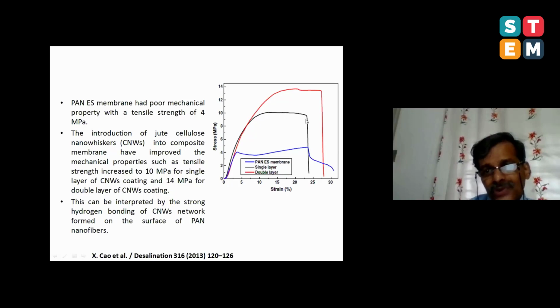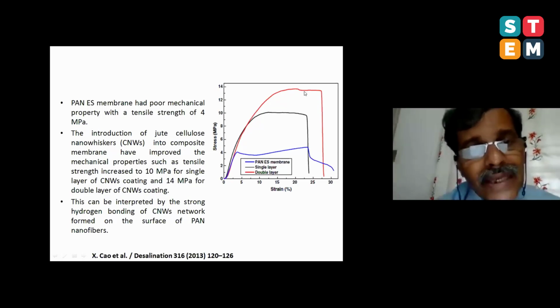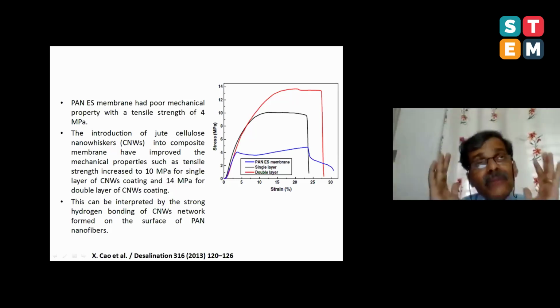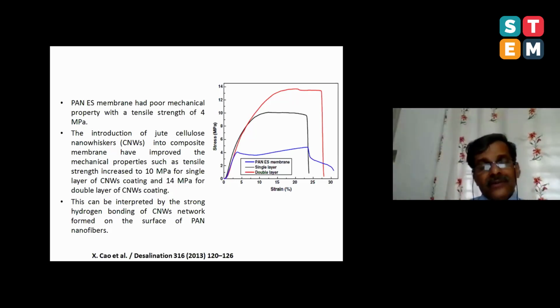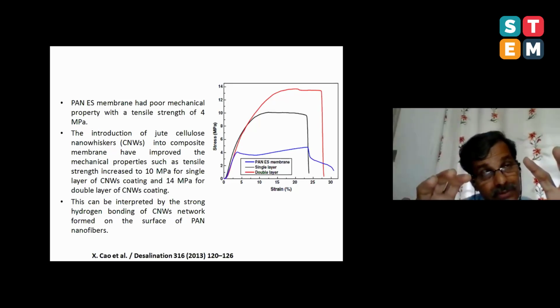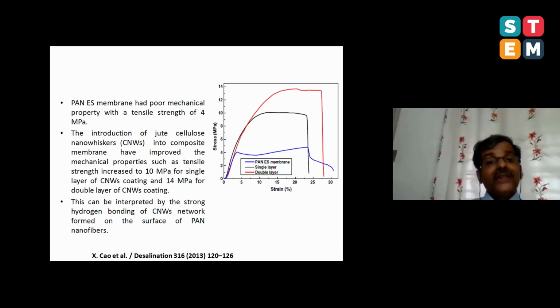But if you coat one side of this PAN membrane with nanocellulose, look at the stress strain behavior. If you coat both sides of this membrane with nanocellulose, look at the stress strain behavior. So what I want to say is, commercial membranes could be strengthened by coating nanocellulose. This is very exciting because many commercial membranes suffer from weak mechanics. So such weak membranes could be strengthened by using nanocellulose.